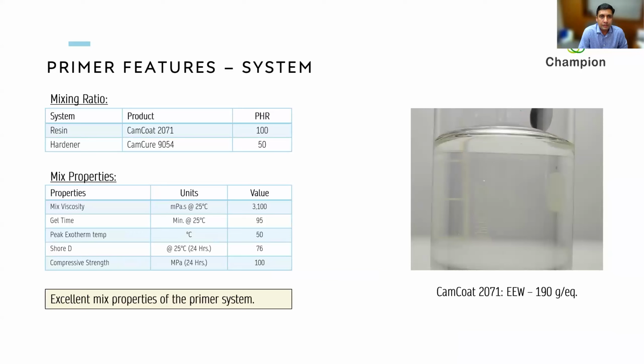Pairing a primer system with CamCure 9054 and CamCoat 2071, which is the basic liquid resin, it's a very convenient mix ratio of 100:50. And you will notice that the gel time is about 1.5 hours, which is very, very convenient. The peak exotherm is only 50 degrees, which is extremely important because this would ensure that the system does not have any heating at the time of application, and it gives a very good surety and compressive strength.